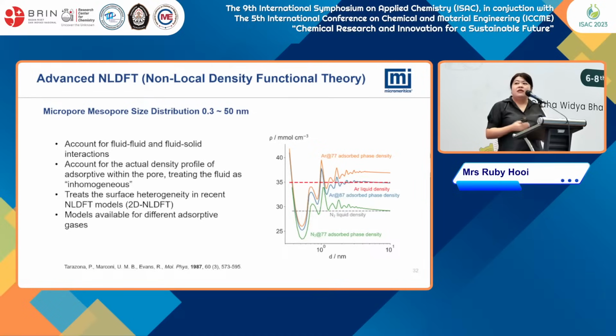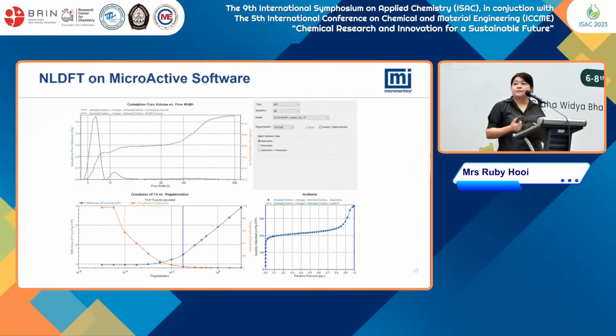With the advanced NLDFT modeling, it's able to look even further below. This is for micropore and mesopore size distributions, because some samples have both micropore and mesopore sizes. The advanced NLDFT accounts for the fluid-fluid and fluid-solid interactions. So it accounts for the actual density profile of the adsorptive within the pore, to treat the fluid as inhomogeneous. We also treat the surface heterogeneity in the recent NLDFT model, which is the 2D NLDFT model, the latest that we introduced. The model is available for different adsorptive gases like nitrogen, carbon dioxide, oxygen, and so on. So NLDFT models are available for selection and easy to fit, whether deconvolution or regularization.